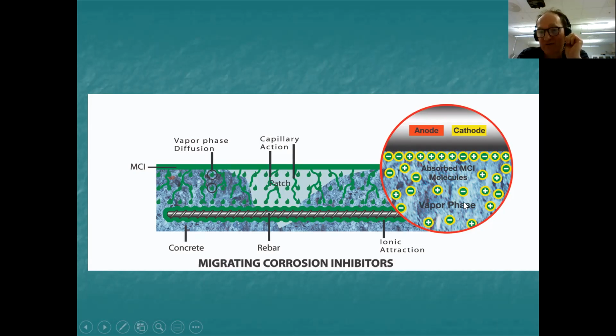So here's the vapor phase I've been talking about, which is occurring inside the concrete itself. And it allows by a diffusion process, the entire rebar to be coated with the inhibitor, shown green in this case. And it's coated by what's called ionic attraction, because in this particular case, the corrosion inhibitor has charges on it, plus and minus.